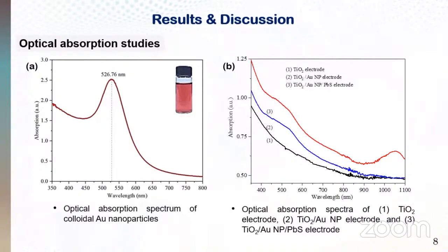And figure B shows the optical absorption spectra of TiO2, TiO2 gold, and TiO2 gold PbS electrodes. Gold nanoparticle incorporated electrode shows a broad peak in the visible region between 500 nanometers and 550 nanometers. This peak clearly confirms the presence of gold plasmonic nanoparticles in the TiO2 electrode. TiO2 gold PbS photoanode shows a similar broad peak around 500 to 550 nanometers. Also, this photoanode exhibits another very strong absorption peak around 1050 nanometers in the near IR region, evidently due to the optical absorption by PbS quantum dots.